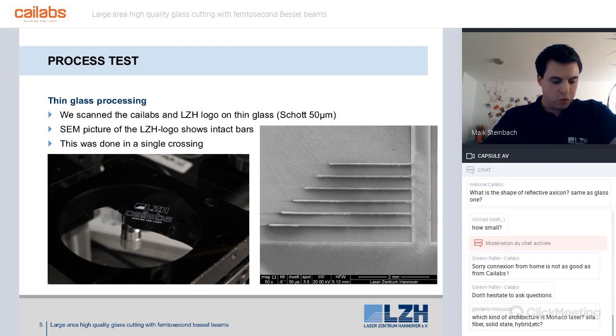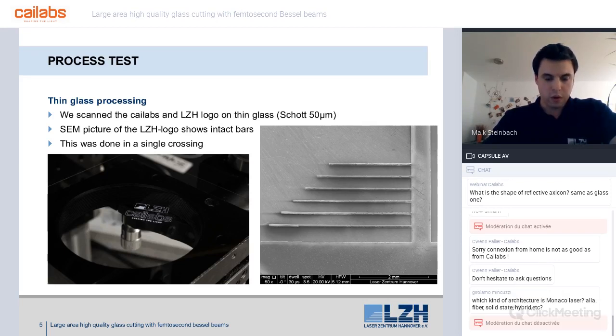We also did some material processing on thin glass. The glass shown here is a Schott glass with a thickness of 50 microns. We processed the Cailabs and LZH logo with a single crossing. If you have a closer look at the LZH logo on the right side with an SEM picture, you can see the bars of the LZH logo being intact and showing a good processing quality.